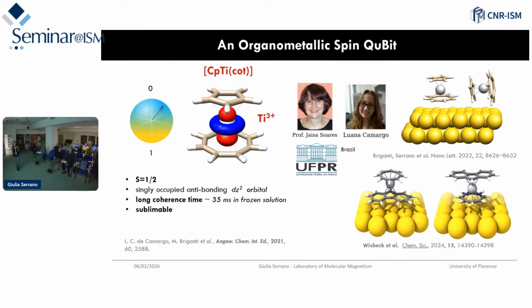Then, concerning this spin 1/2 system, one of the most interesting systems that we work with is this CpTiCOT molecule, synthesized by Jaisa Soares' group in Brazil, in which you have a titanium 3+ ion sandwiched between two carbon-based rings. This is a cyclopentadienyl ring with 5 carbons, and this is with 8 carbons. The nice part is that you have a magnetic orbital pointing potentially towards the surface, the dz² orbital.